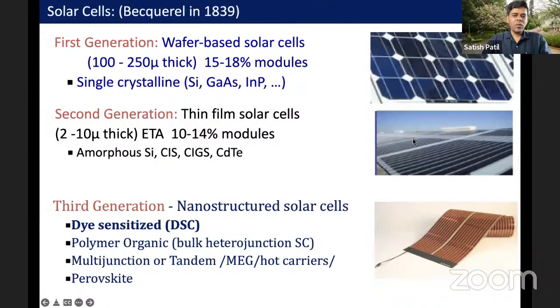So to overcome the cost, these are some of the proposed alternative materials. But again, they face a lot of limitations. For example, cadmium telluride is a very toxic material. Amorphous silicon has a lot of defects, but you see that from single crystalline silicon to amorphous, there is a change in the material requirement.